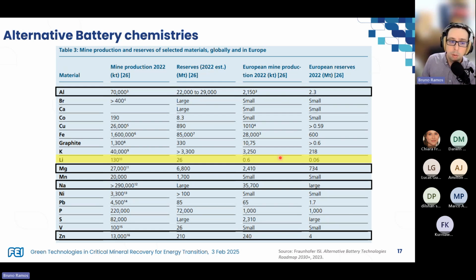If we compare with sodium, for example, the reserves are much larger, and the current mining production is already quite high, it's just that they don't know how much there is. They just put "large" here because it's a very big amount of reserve. Same thing goes for magnesium. Zinc is a bit more limited, but still quite a lot, and aluminum, there's plenty of aluminum around, especially not so much in Europe, but around the whole world. So transitioning from lithium to these can be very strategic in terms of availability.